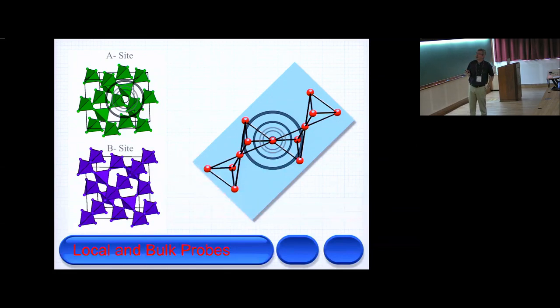In muons, the muon will sit somewhere, in most cases, very close to an oxygen. Where that is is always a controversy in the studies, but it sits in an interstitial site. There might be many of them in a system, and they have to work out what is going on there. So those are local probes. You can also get the local structure from this total scattering approach to neutrons, where you really look at the background, where most of us throw the background away. It's just too much work to look at. Or X-rays can do that.